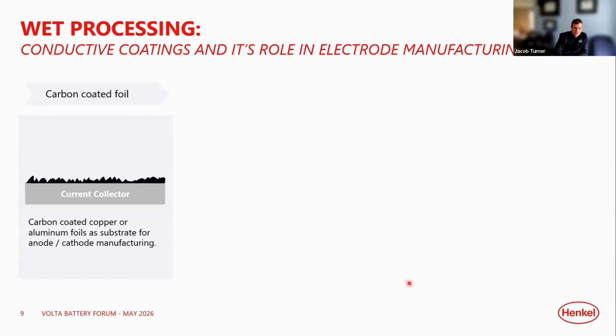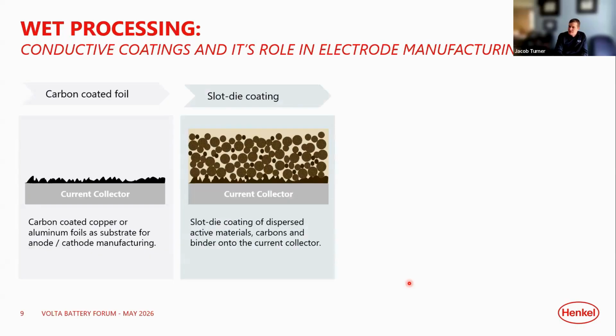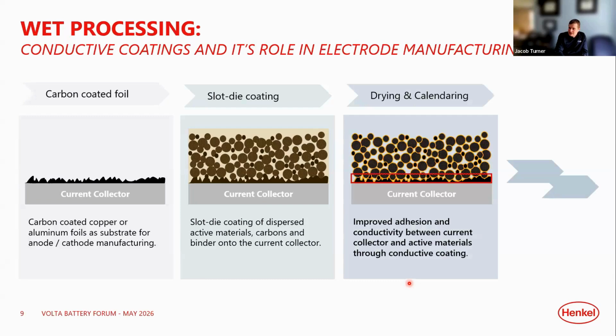So when we look at the wet processing, this just walks us through. We have the increased surface roughness from this conductive coating. And then as that active material slurry is deposited, there's this natural filling of that increased surface area space to start to form this interface that we want, that is well adhered and helps facilitate electron transport. This interface further gets modified during the drying and calendaring step, where these materials get forced together within that increased surface area. And we see enhanced adhesion when using conductive coatings as compared to bare foils.